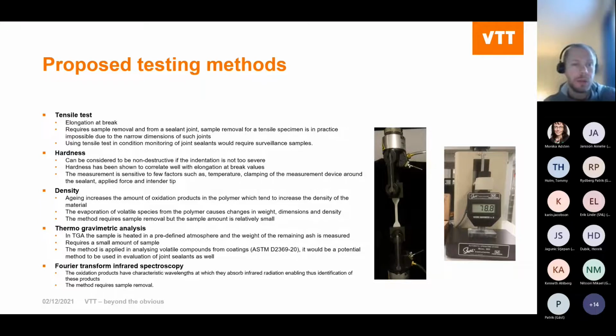Then we have hardness measurements. It can be considered non-destructive, especially if the indentation mark is not too severe. And hardness is a good measurement method because it has been shown to correlate quite well with elongation at break values with several polymers. However, the hardness measurement is sensitive to a few factors such as temperature and how you clamp or attach the measuring device around the sealant, then the applied force and indenter tip. But most of these factors are such that you can minimize their effect by using standardized methods.